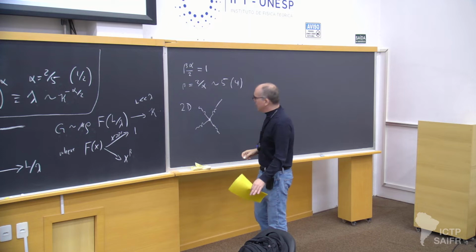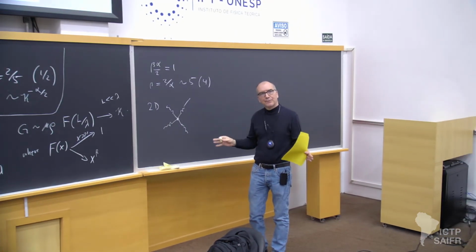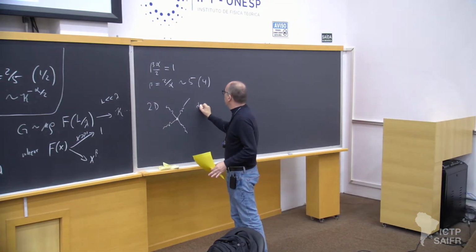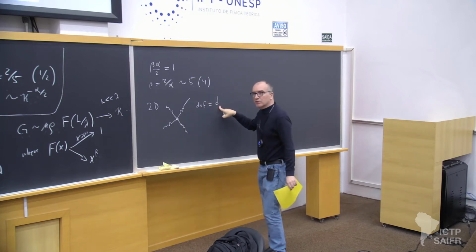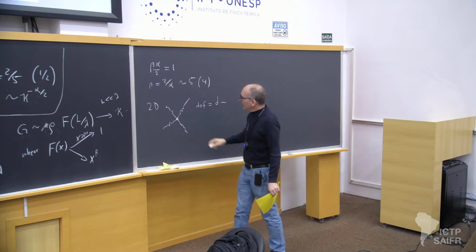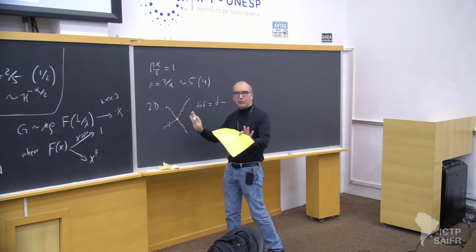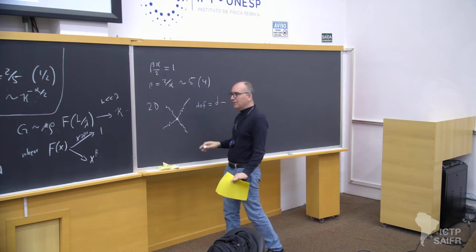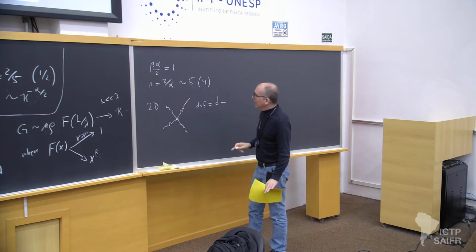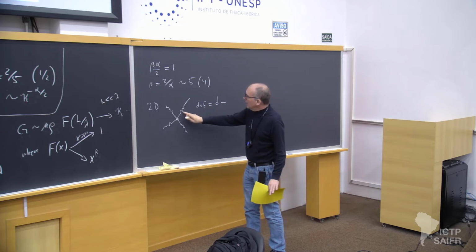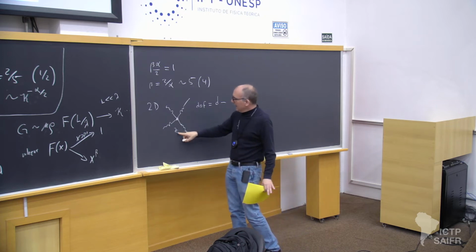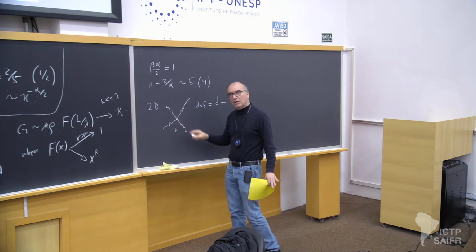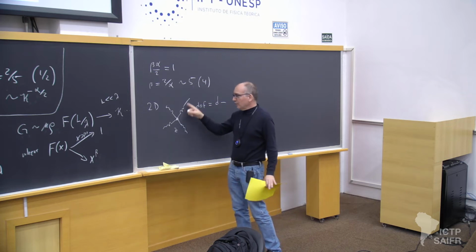If I look at one typical node in a network, it has a number of degrees of freedom, which would be D, the number of dimensions I'm in. And I would subtract off from that, now this is a central force picture with just spring constants, the Z, or Z, depending on where you come from, neighbors that you have at a typical node, divided by 2, because each one of these constraints is a half a constraint for the 2 nodes it's connected to.